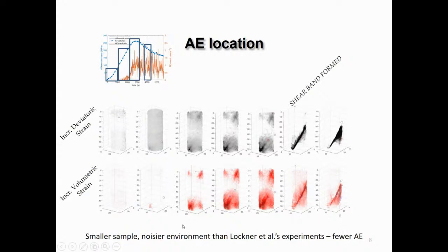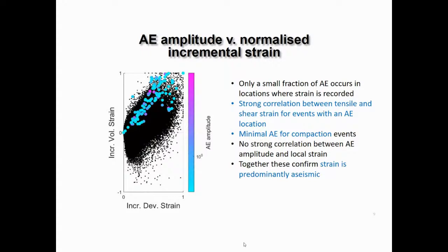So we don't have as many data points to compare as the Nature paper by Dave Lockner's group, because we've got a smaller sample, so we've got fewer acoustic emissions. But we can back out some inferences from this. We find that there's a strong correlation between the volumetric and the deviatoric strain, or the dilatant and the shear strain. And that's because we've got this mixture of tensile cracking and shear right on the shear band. Also, dilatancy makes it easier to shear something past another rough object. So it's maybe not surprising that there's a high correlation.